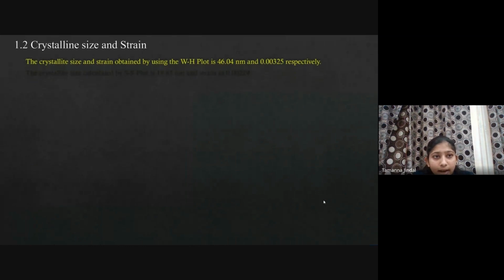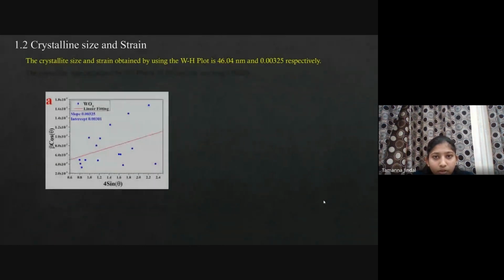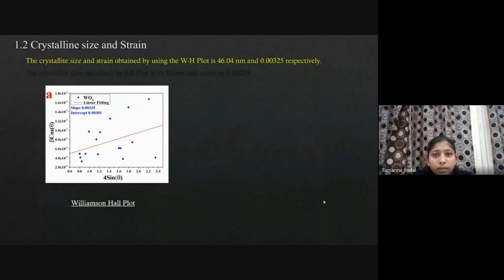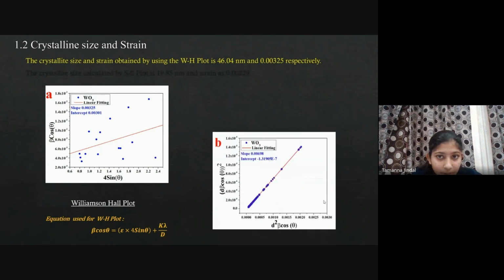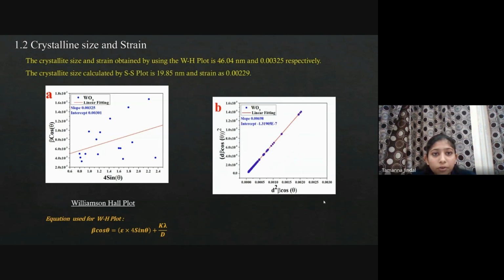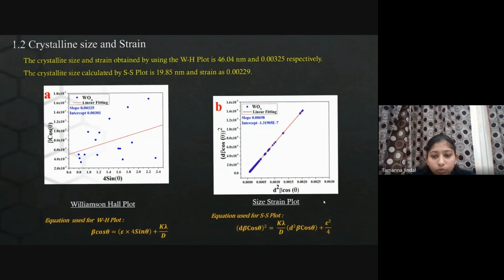After that, crystallite size and strain were obtained using the Williamson-Hall plot, and the crystallite size was found to be 46.04 nanometer using the equations, and the strain to be 0.00325 respectively. Finally, the crystallite size calculated by the size-strain plot is 19.85 nanometer and the strain is 0.00229 using the equation. Now, absorption spectra by UV-visible spectroscopy.